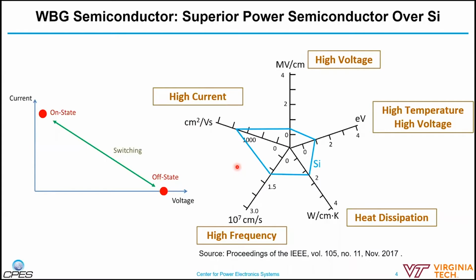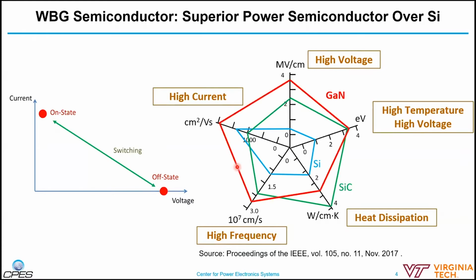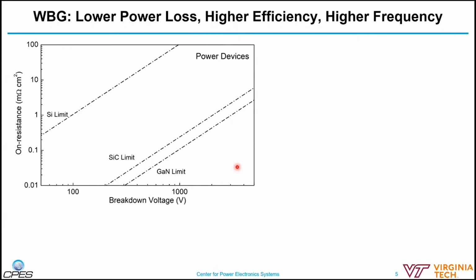Okay, so now let's look at what silicon can offer us, and then one of the wide bandgap semiconductors, silicon carbide, which has a bandgap of about 3 eV, and another wide bandgap semiconductor, gallium nitride. So from here, you can see that gallium nitride and silicon carbide are much superior power semiconductors compared to silicon. Okay, so how do these benefits translate into power device performance?